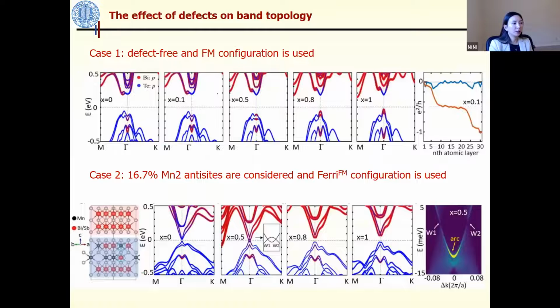Yes, they use the supercell. So do you need to do some kind of average about the defects location? Yes, right. Even if we consider the antisites, we put in 16.7% of manganese antisites, it still doesn't represent the real crystal structure. Why is that? Because this is not random antisites, but rather so-called periodic antisites.